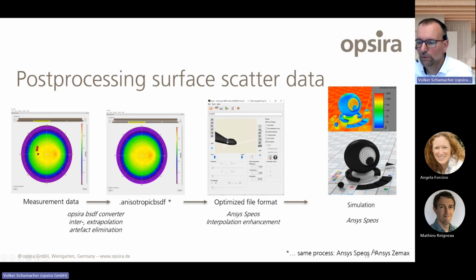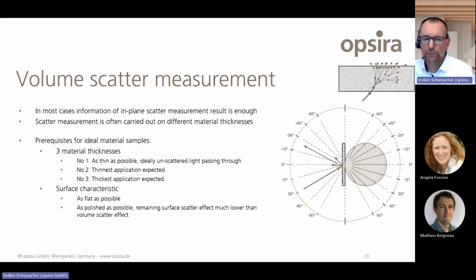And the same is valid for Ansys Zemax. And we see here a black material, and we also see some specular effects here and there. And this happens on such a black material at a very flat angle of incidence. There, this material becomes more and more specular. And all these effects are integrated in the measured data. This is for surface scatter characteristic.